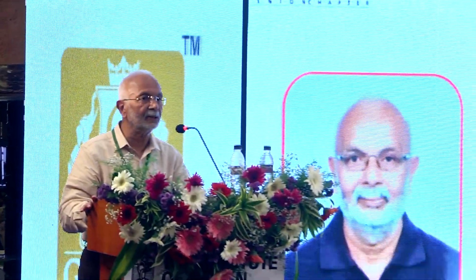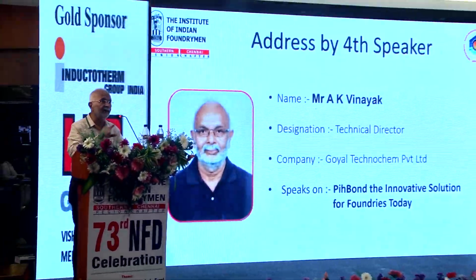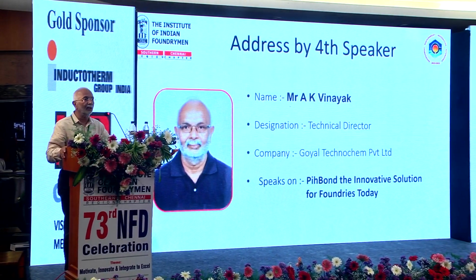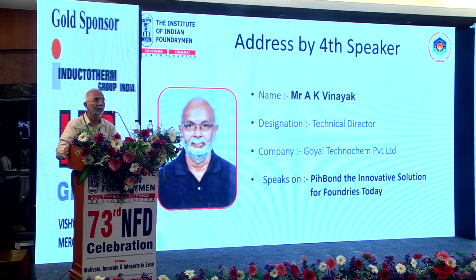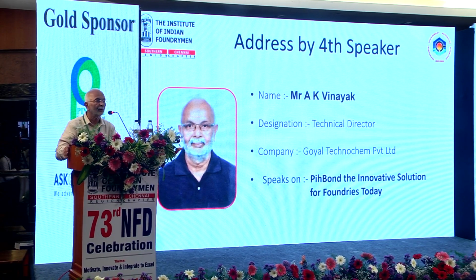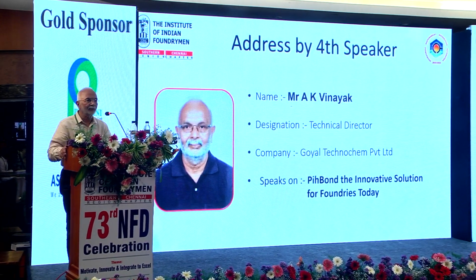And as far as warpage is concerned, because of its higher strength, both in the form of GCS as well as DCS, the warpage will definitely reduce. Because the major concern is uniform machining allowance required when you are doing big castings. Yes, this has helped.